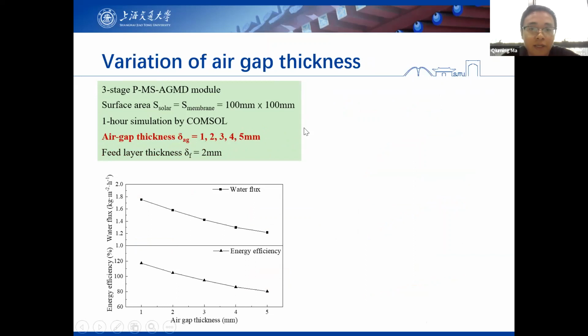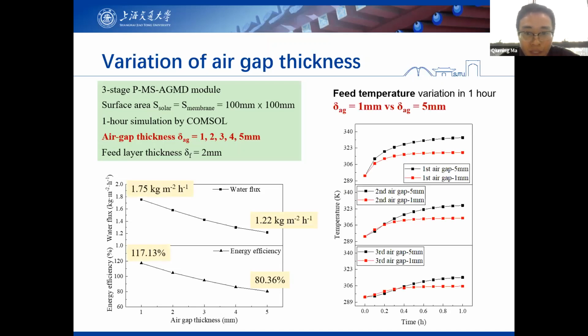And after the feed layer thickness, then we varied a little bit of the air gap thickness. The similar trend we found is with thinner air gap thickness, also the performance were better. But differently, actually for thinner air gap thickness, each layer, the temperature is somehow lower than the thicker air gap thickness setting.